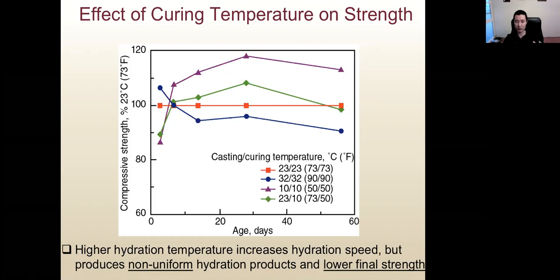However, because the hydration product grows so fast, it will produce a non-uniform hydration product. So the chance for the concrete to have a certain type of flaw will be higher. That will generate weak zones in concrete, so that will reduce the final strength of concrete. So the faster the hydration speed when we increase temperature, that will actually decrease the final strength of concrete.